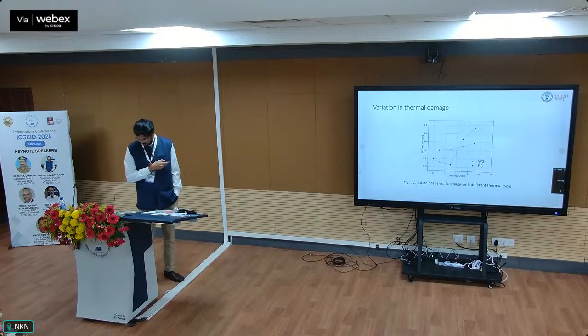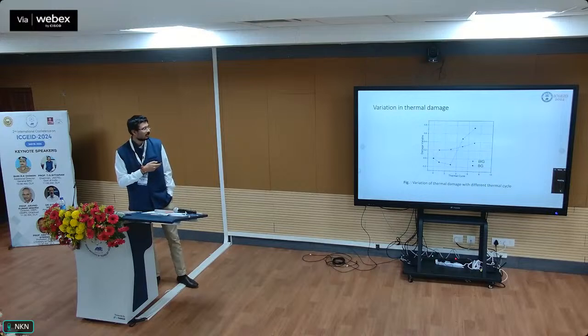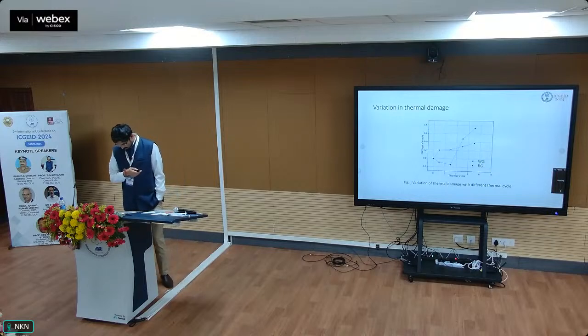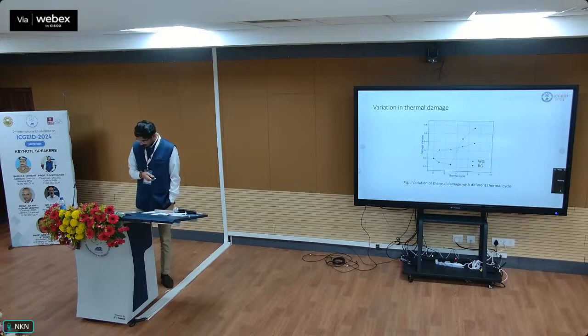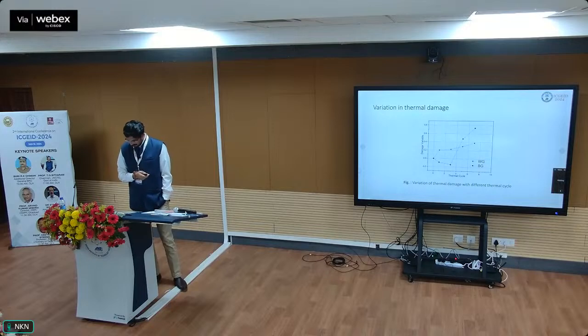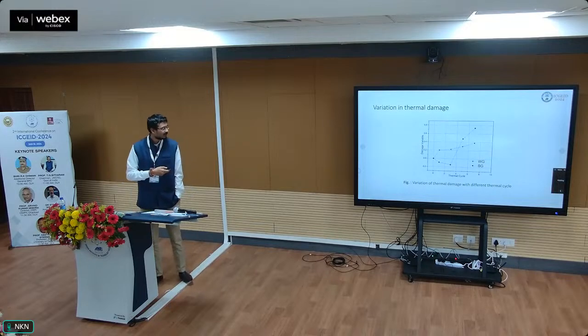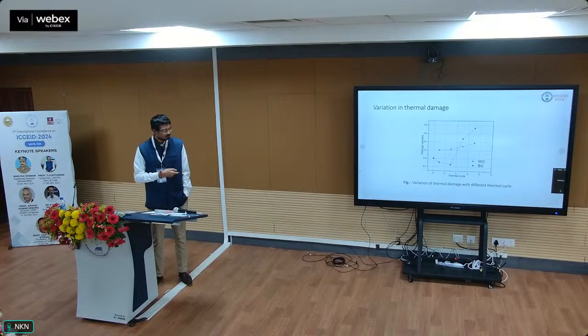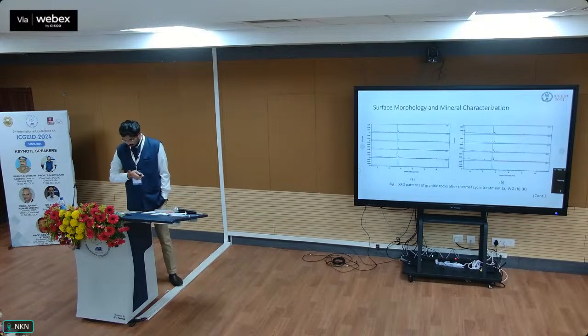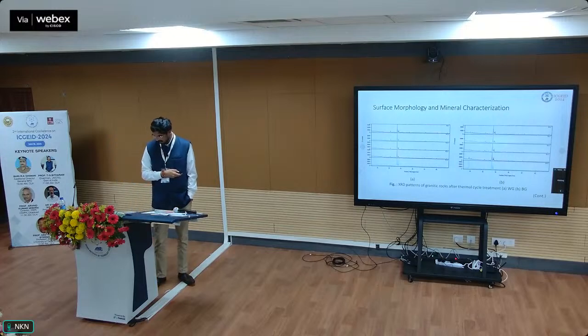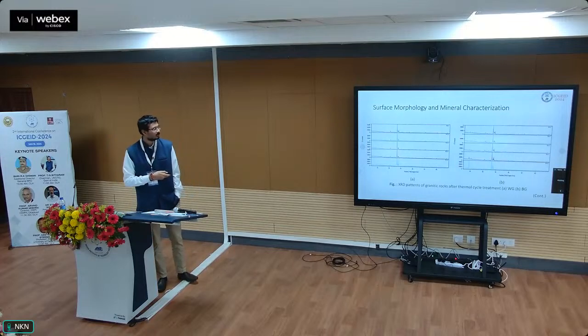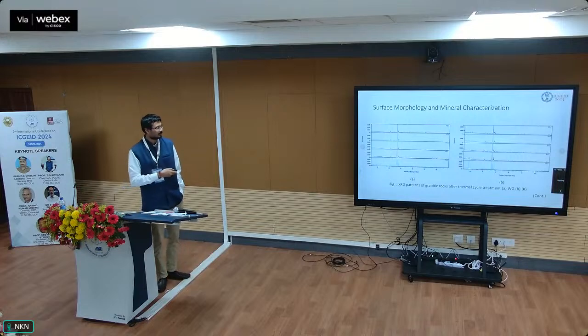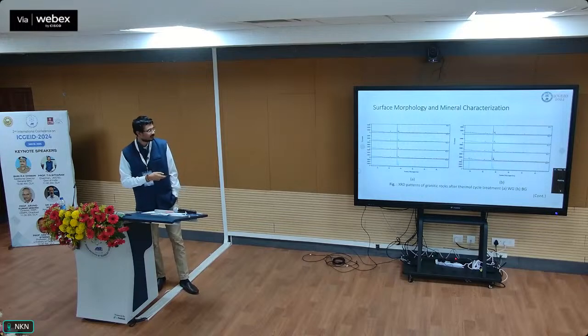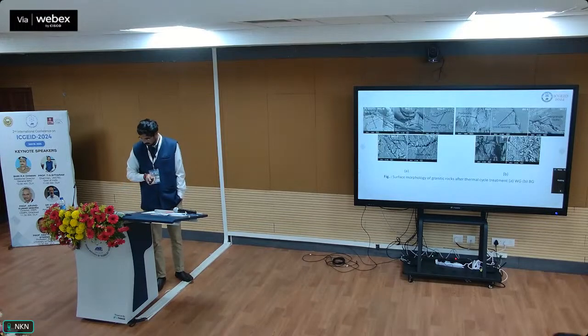Further, we have taken the damage variables with thermal cycles. So basically what we are observing, the white granite is showing more localized, less distributed damage, and black granite is showing much more distributed damage. We have also conducted XRD analysis, and we have found that there are not any significant mineralogical changes in the rock samples with the increase in heating cooling cycles.